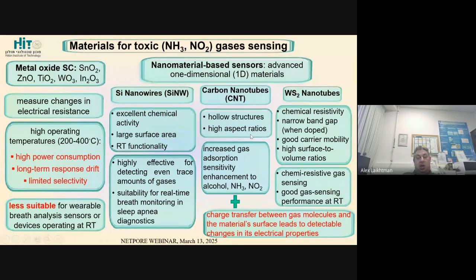If you add to these nanotubes, for example, carbon nanotubes or WS2 nanotubes, we have even better characteristics. Carbon nanotubes have hollow structures and high aspect ratio, so they have increased gas absorption sensitivity, with enhancement to alcohol, NH3 and NO2 as a breath test. Probably alcohol, not all of us are quite happy with this development. Some consumed before driving and so on.